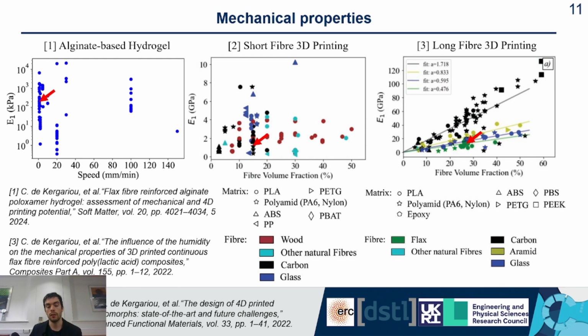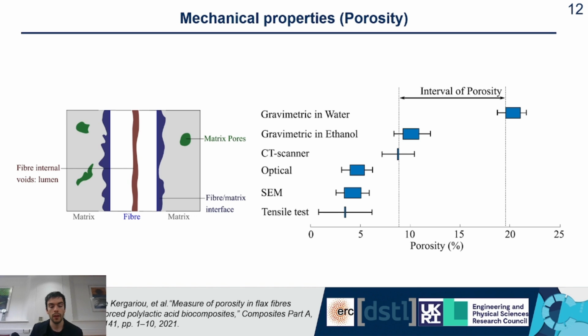You can just choose the stiffness that you want, depending on the function that your actuators will have. Another aspect that I'm not going to go into much detail about: when we started working on natural fiber, there were not clear guidelines on how to measure the porosity of natural fiber composites. However, porosity has an impact on actuation and on mechanical properties, because there's an impact on water absorption as well. And so we created a comparison between different techniques for measuring porosity: gravimetric measurement in water and ethanol, CT scanner, optical measurement, SEM, and tensile test.